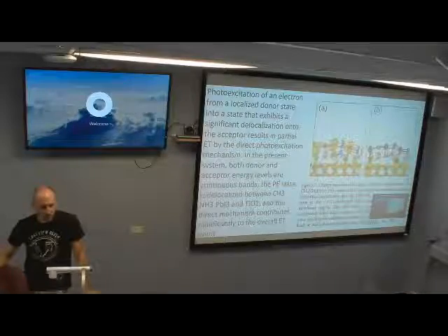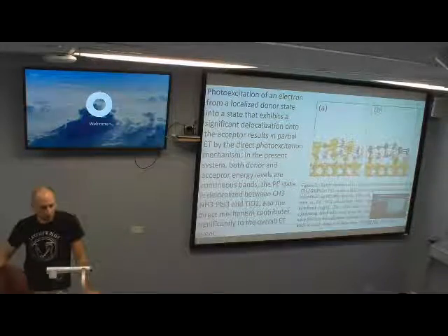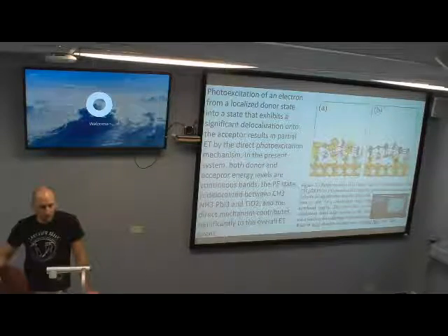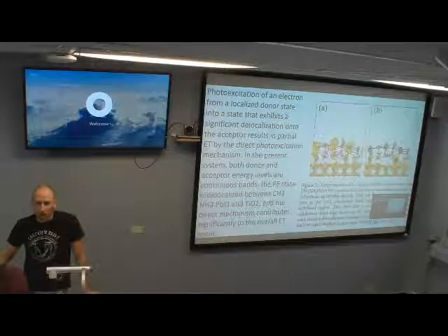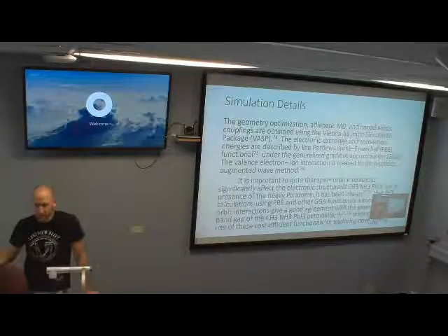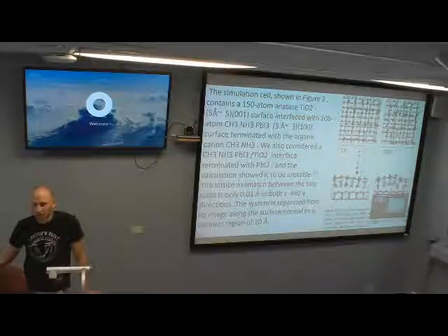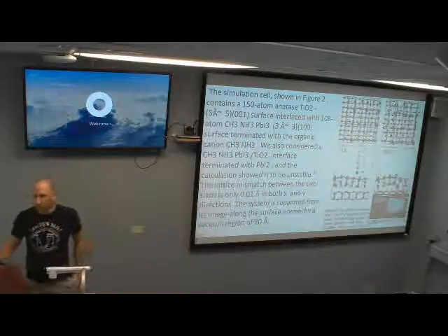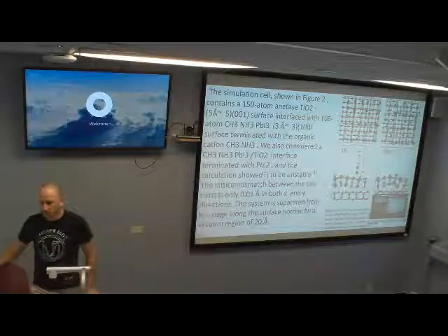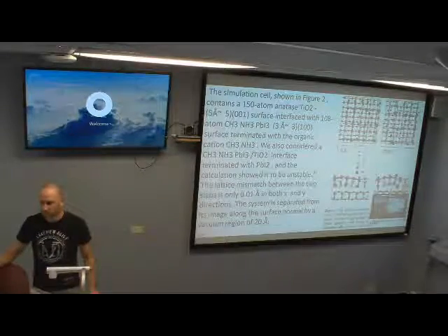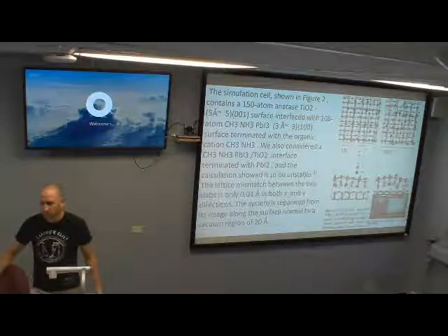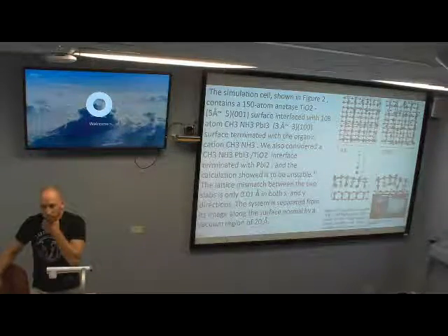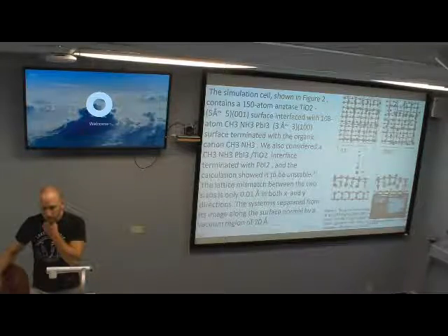There was John's question about the cation. Is there any reason that they put all the cations in the same alignment? I think they just optimized it like that. But as we know from Daniel Ramirez, one can expose different surfaces of perovskite, either cation rich or lead iodine rich, or pristine. Why did they select the methyl ammonium cation rich surface facing the titanium dioxide?